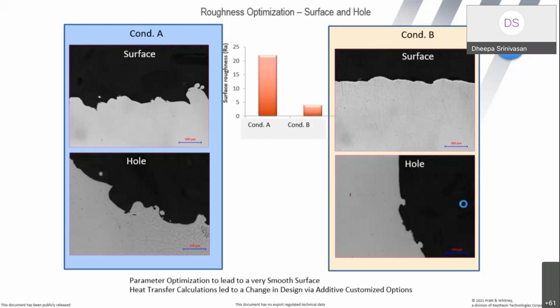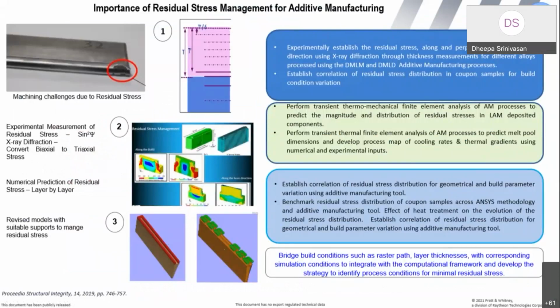We move on to the sixth challenge. Having addressed these, we next tried to build more coupons. We call this a trailing edge nozzle coupon in the build plane. However, when we try to do that, look at challenge number 6. Challenge number 6 is very, very important, namely that of residual stresses that creep into the component. All of us in the welding world would have definitely come across residual stresses, as the weldment will be in a tensile stress state. However, here, additive is a layer by layer welding and solidification process.